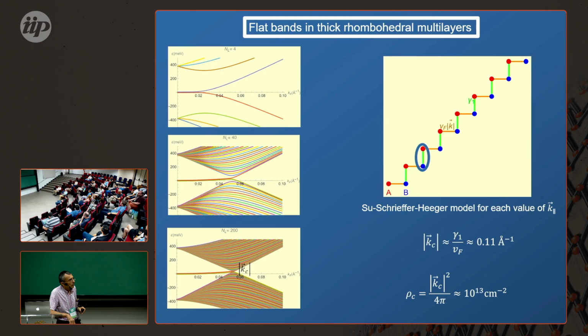But if the Coulomb interaction plays an important role, then you can change the density, right? You would expect, as a function of density, with the screening, there should be a dome. There is a problem: the Moiré systems are way dirtier than the rhombohedral twisted systems, and I imagine the Wigner crystal is very sensitive to disorder. That's a possibility why people have no good evidence for Wigner crystals in twisted systems. But definitely there is not... but we haven't checked for that. Not even in the less disordered ones, right?